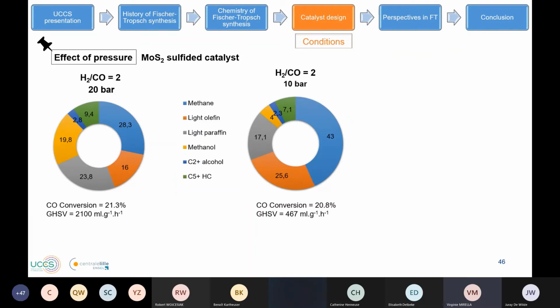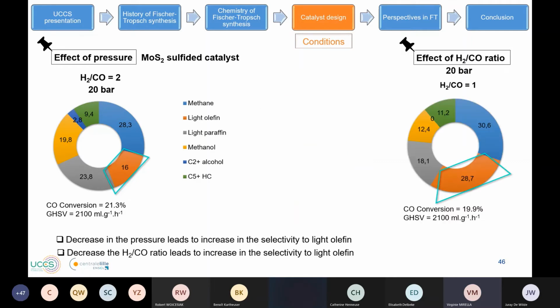We have also varied the conditions. We have seen that, for example, when we decrease the pressure, we increase the selectivity in olefins. And we have seen also that when we decrease the ratio of hydrogen to CO to 1, so we have less hydrogen relative to CO, we also increase the selectivity to light olefins. So to find good conditions to produce olefin selectivity is really important on this molybdenum sulfide catalyst. So for conditions, we need to work better at low pressure and with low hydrogen to CO ratio also.